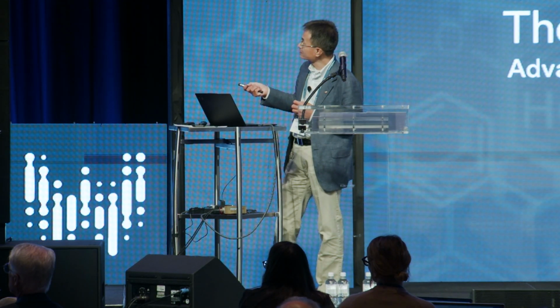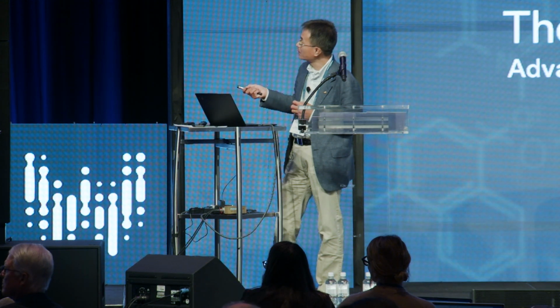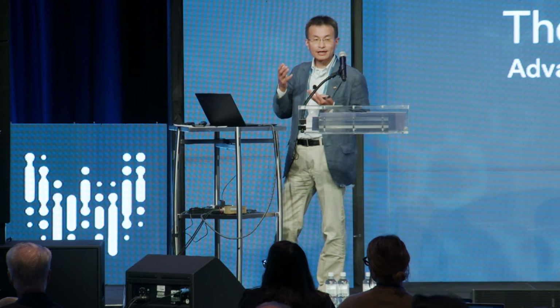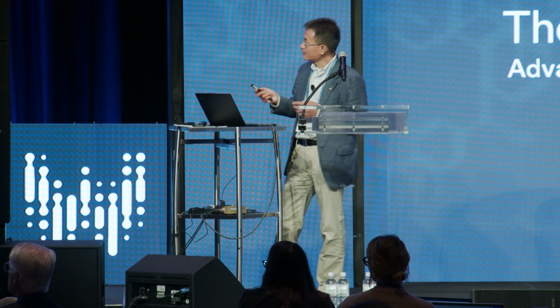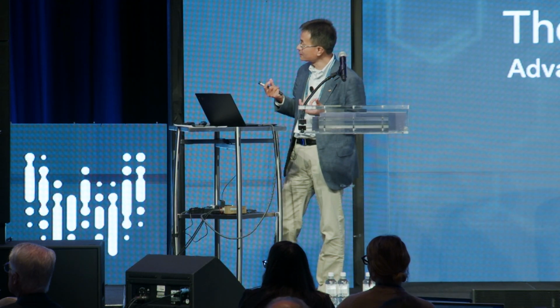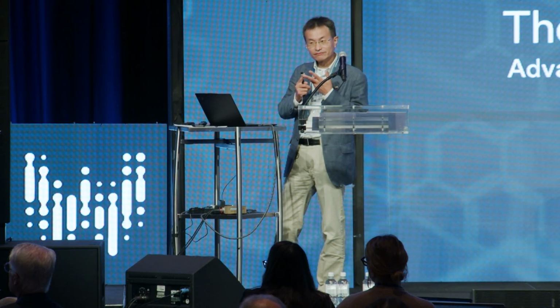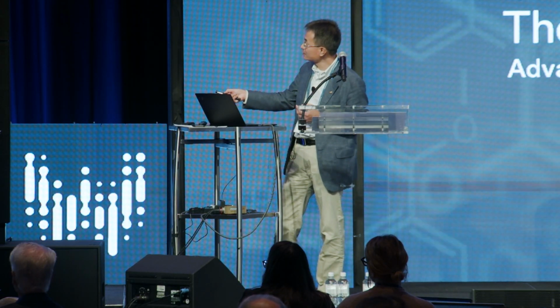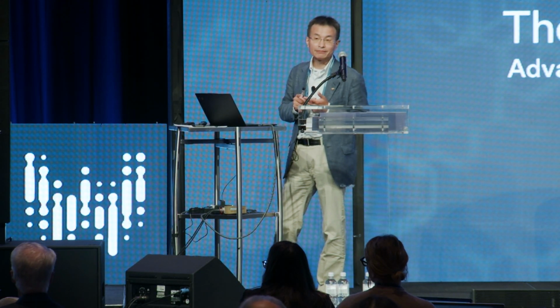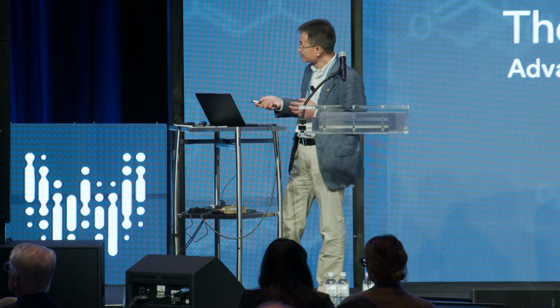In the so-called vapor-liquid-solid process, you will see this semi-spherical particle in a chemical vapor deposition system at a high temperature, and that's the liquid. When we use this VLS methodology to grow these one-dimensional crystals, you have a vapor phase, for example silane or germanium vapor, and that's the vapor source. Then the solid is the single crystal of silicon and germanium. That's what we call VLS. So this certainly goes back a long, long time ago.